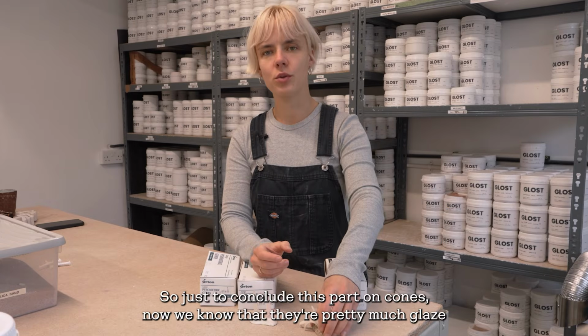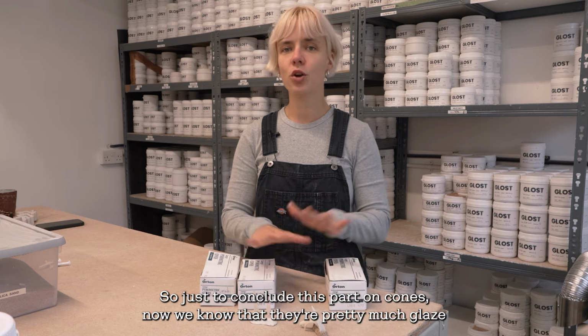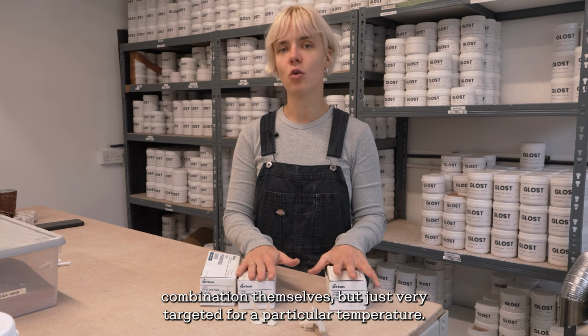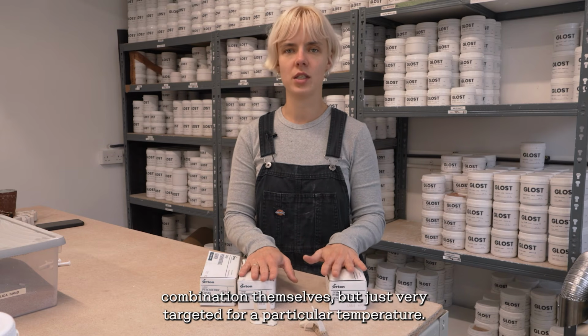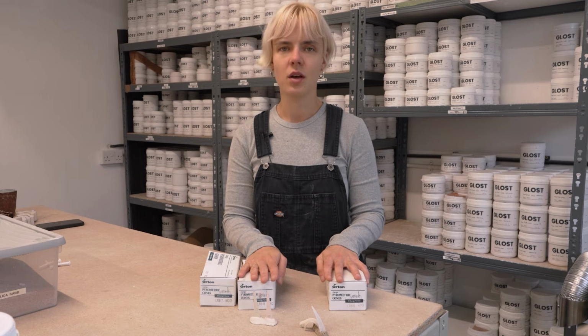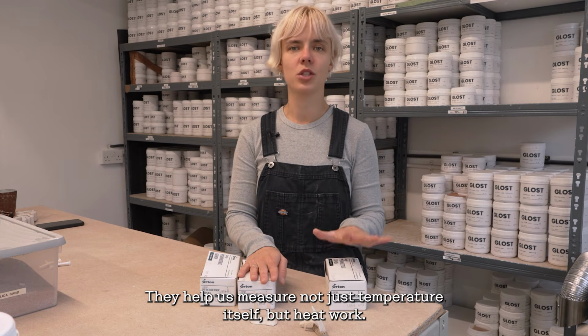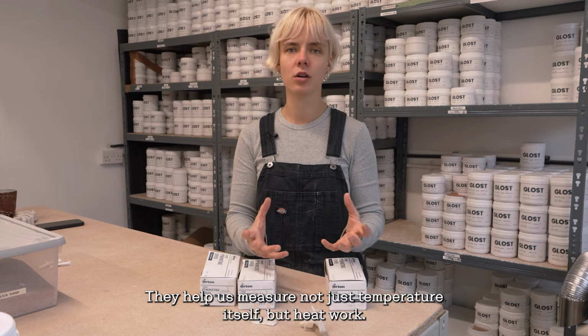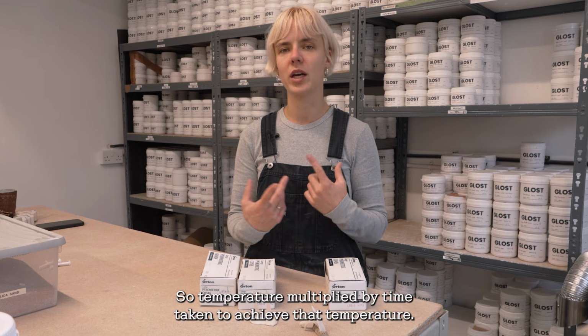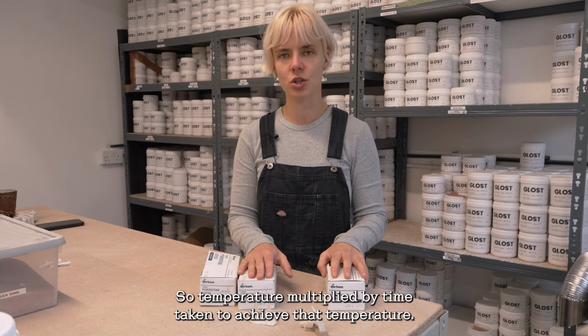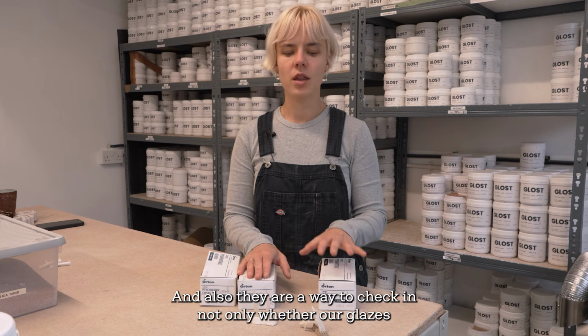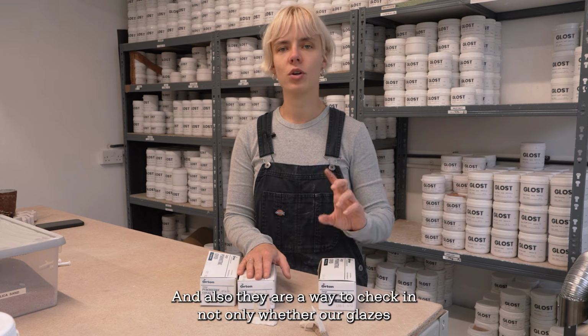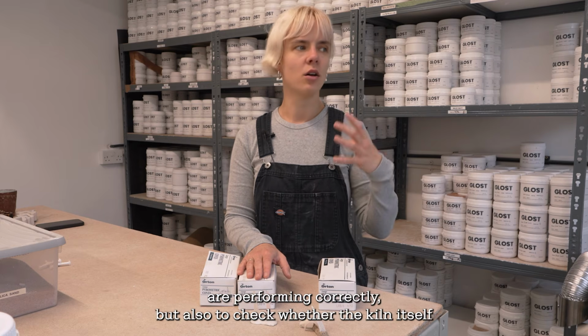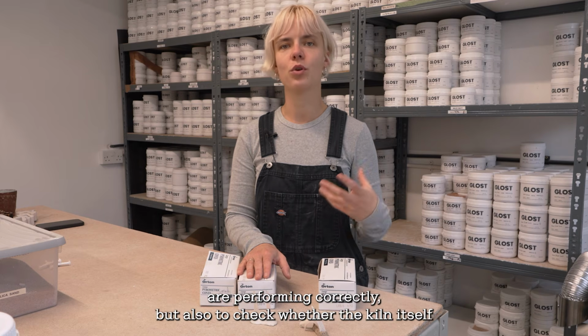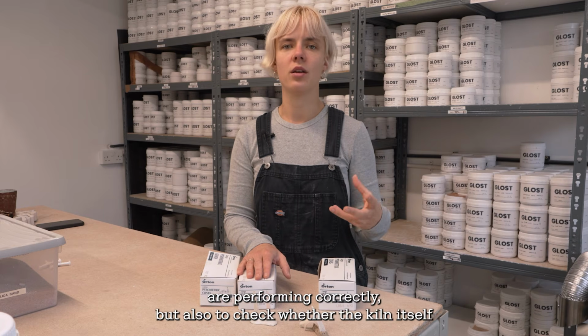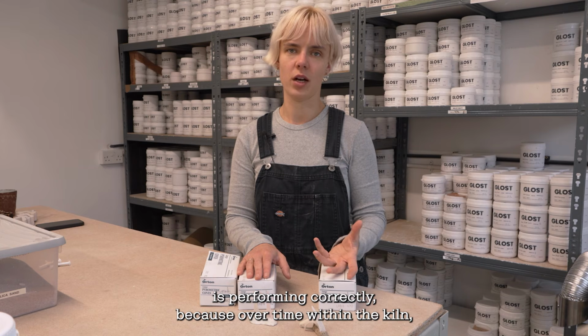So just to conclude this part on cones, now we know that they're pretty much glaze combinations themselves, but very targeted for a particular temperature. They help us measure not just temperature itself, but heat work. So temperature multiplied by time taken to achieve that temperature. And also they are a way to check in not only whether our glazes are performing correctly, but also whether the kiln itself is performing correctly.